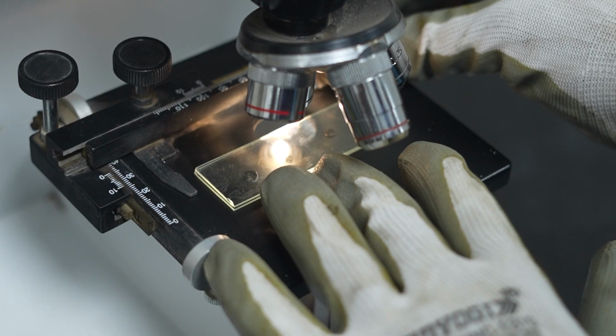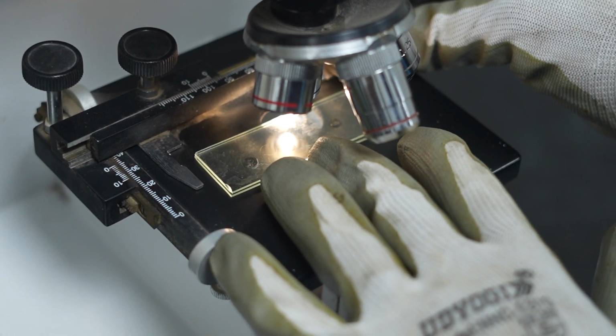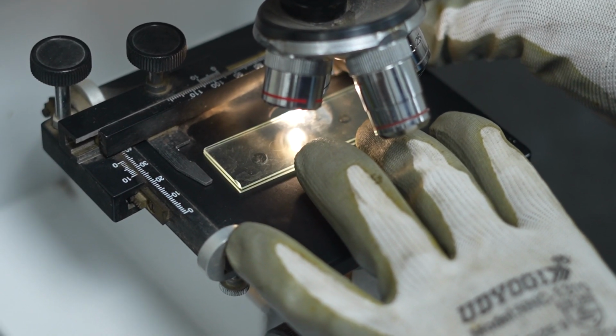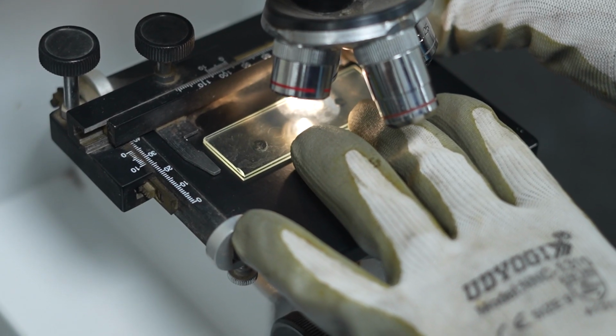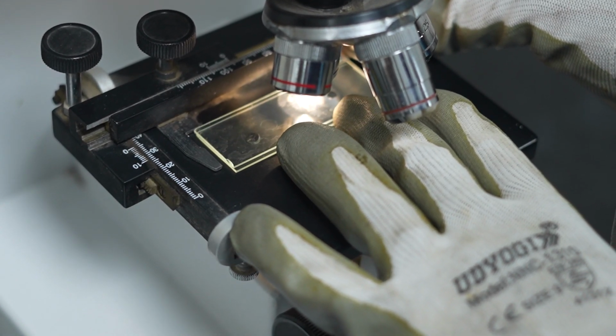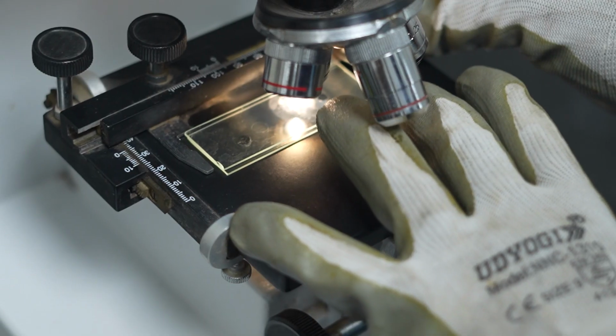The prepared sample is then examined under a carbon black dispersion tester at 200x magnification with a field of view of 1 millimeter in diameter. The test evaluates whether the carbon particles are evenly distributed throughout the material. The dispersion must be uniform with no visible agglomerates or clusters. Any excessive agglomeration or uneven distribution is considered a failure.